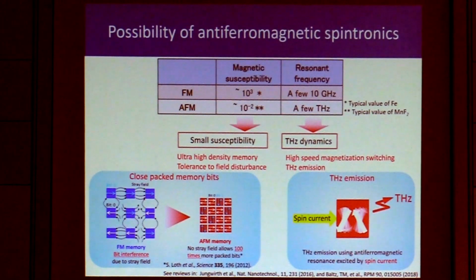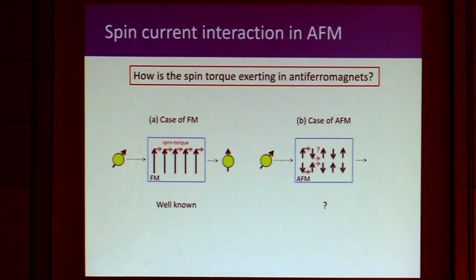So when we started this antiferromagnet spintronics, the very basic fundamental question was how the spin current interacts with the antiferromagnet. In the ferromagnetic case, it is very well known. When we inject a spin current into the ferromagnet, the magnetization feels a spin torque. And when the spin current is large enough, we can flip the magnetization into the other direction. However, for the antiferromagnetic case, it was not really clear at that moment.